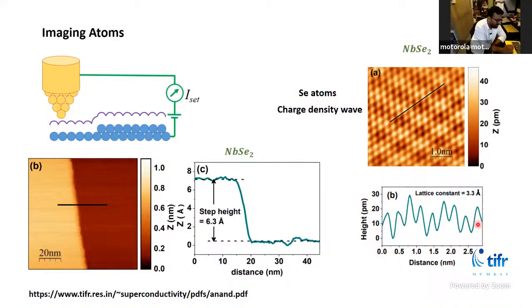Now, one more thing which is very particular to this material is that you can see this sort of checkerboard pattern also coming alongside the positions of atoms. This is actually the charge density wave. This is a property of this material: the electrons place themselves in such a manner that the charge is not uniform everywhere, forming a wavy pattern. And that you see as this checkerboard pattern. That is not because of the height variation. No, this is not because of the height variation. This is actually because the probability of having your electrons here is higher than having them here. This is a material property, a consequence of how niobium and selenium come together to form this material.